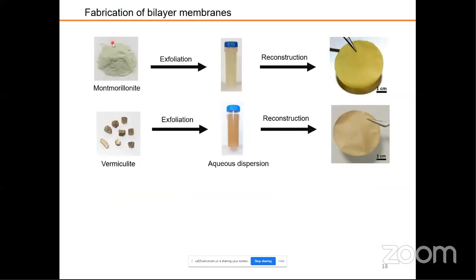It comes in a powder form. Then we can exfoliate it into individual layers and make a two-dimensional film. Similarly, vermiculite clay we can also exfoliate into an aqueous dispersion and make a two-dimensional film. What we have done now is combine these two membranes. On one side we have put montmorillonite clay, on the other side vermiculite clay. It's a bilayer membrane, a membrane of two clays, montmorillonite and vermiculite, and both have different properties because they have slightly different structures.